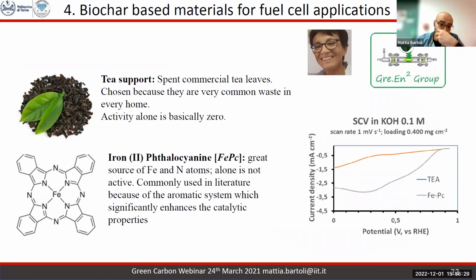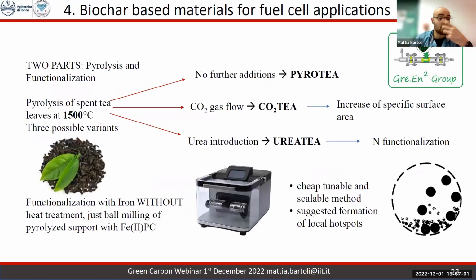derived from tea, that is practically a zero active material in this kind of catalysis, with a pre-catalyst, the iron phthalocyanine, with a system merging the green chemistry 8 points approach with what we want, keeping the performances high and the tailoring process scalable. So we try to ball mill it after high temperature annealing the biochar. This is the weak point of this work.